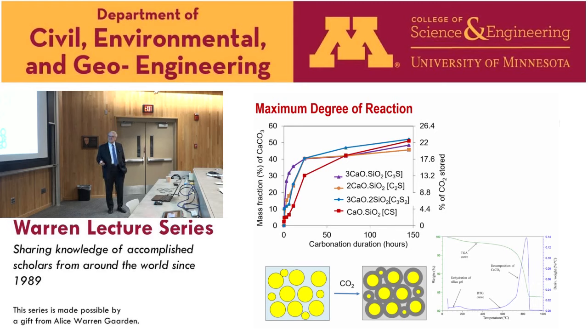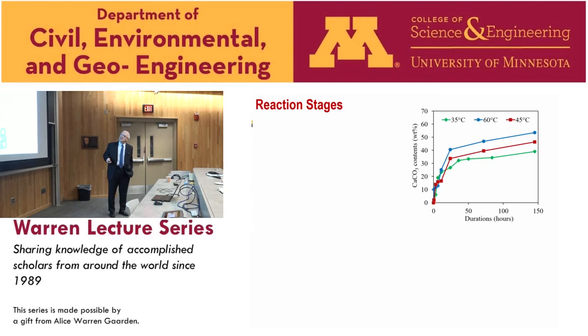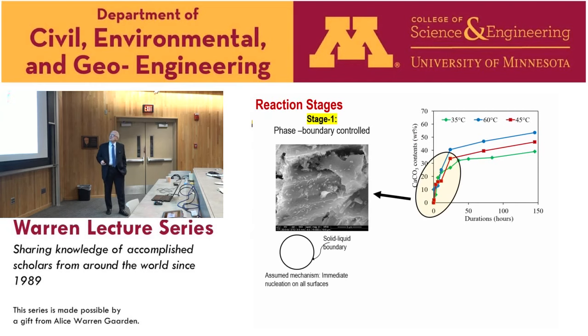Now, we take the cement grain, we expose them to CO2, we form those layers of silica, and we can use various techniques to determine how much calcium carbonate we have. So we look at those reaction stages, and we look also at the microstructure that is associated with it. And in the first stage, you can see this is a cement grain with a little speckles of material. That's a calcium carbonate that starts forming on the surfaces of this material. So the calcium carbonate forms at the solid-liquid boundary.